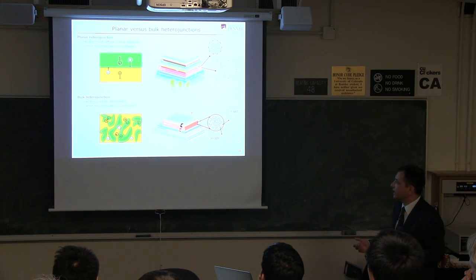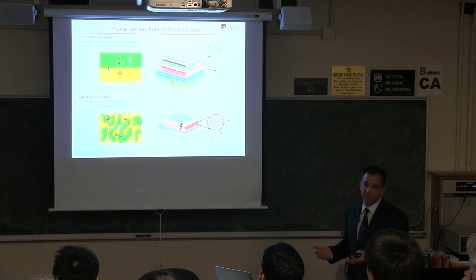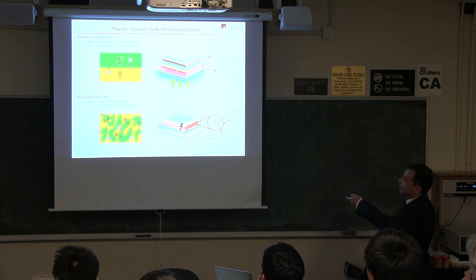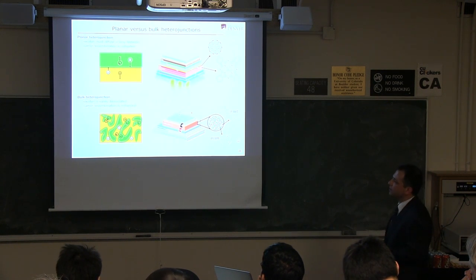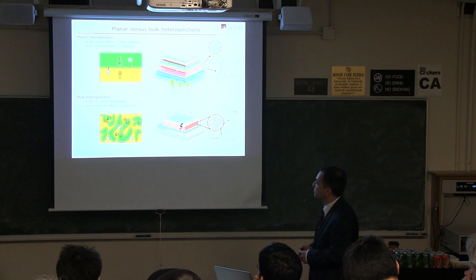The exciton diffusion length is 3 to 5 nanometers in organic semiconductors, typically. So light that's absorbed far away from the interface, say up here or down here, simply won't make it to the interface, and you won't be able to harness that energy.